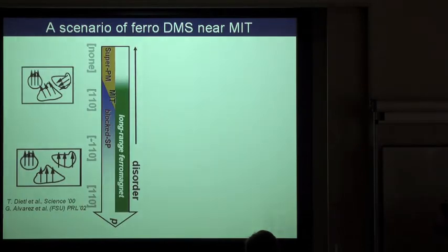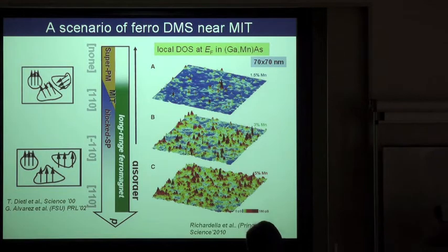But also nowadays, we can see by scanning tunneling microscopy work at Princeton, in collaboration with Santa Barbara, and this work shows beautifully that we have this fluctuation of local density of states. This local fluctuation of density of states is visible here, and also visible here are samples with different concentrations, so we have strong Anderson localization, weaker localization, still weaker, and this data were taken at the Fermi energy, and this also represents the Coulomb gap: if you have very few states, a big Coulomb gap, low densities of carriers, remember that was an acceptor, we have a little higher density of states, and at the medium concentration of the metallic state, we have much higher density of states. But an important point also is that we see that this local density of states fluctuates.